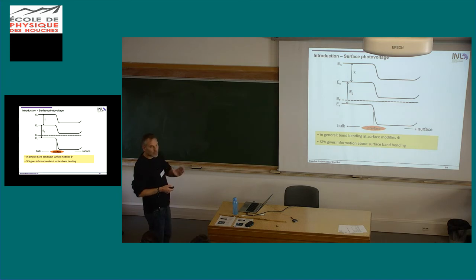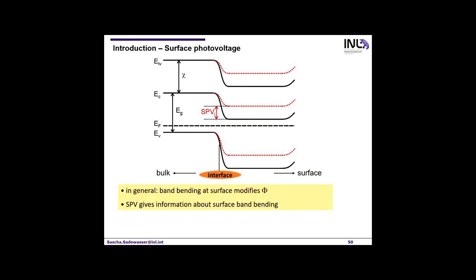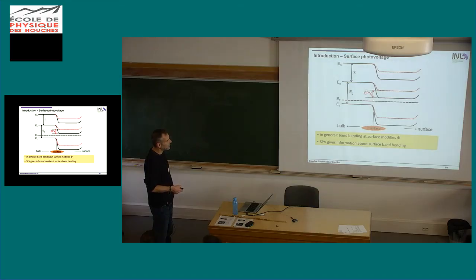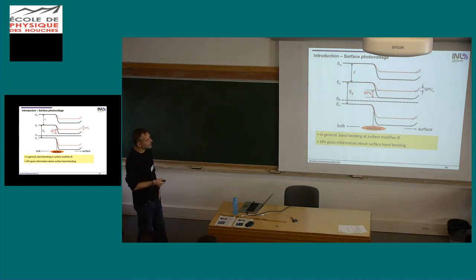Because the light goes deep into the material, we can actually not only measure what happens at the surface, but we can also measure what happens at a PN junction, for example. So again, here, light might be absorbed here. Normally, this would be, for example, a window layer. So light goes through and we absorb here. We generate charges, and then we can also change that band bending at a buried interface. So we measure at the surface something that happens at an interface inside the sample. And this is also convoluted with whatever changes at the surface. So it's not easy to separate the two parts, but the total surface photovoltage that we measure can come from interfaces and from the surface.